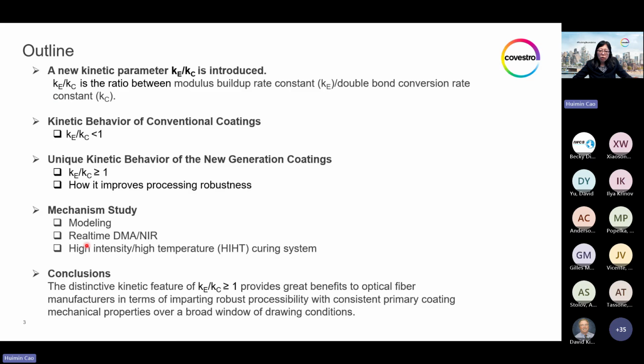And in this study, we introduced this new parameter, the Ke over Kc ratio, and I will explain why for all conventional coatings, regardless of fast or slow cure, this ratio is always less than 1, which means modulus buildup is slower than conversion. But our new generation coating starts to show a breakthrough behavior of Ke over Kc ratio equal to or even higher than 1, which you will see how this feature greatly improves the processing robustness.